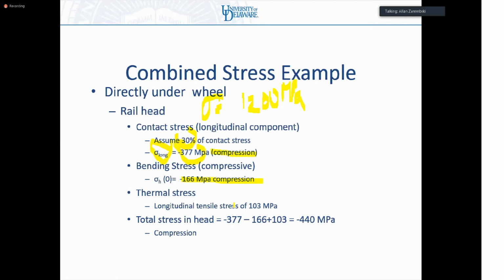And let's say for a moment, it's a very cold day. And so this was the second case that I didn't do, where the rail temperature is below the ambient temperature, so I'm in tension, and I have 103 megapascals tension. So directly under the wheel, I have my minus 377 contact stresses, my minus 166 bending stresses, and my plus 103 thermal stresses. So I have a total of 440 megapascals. All three are in play.